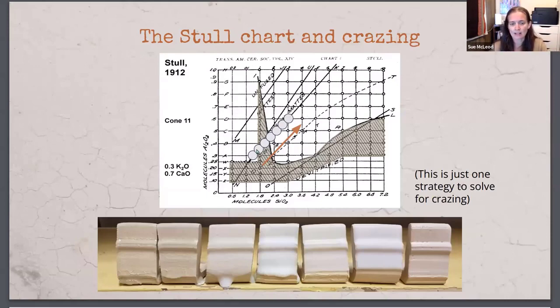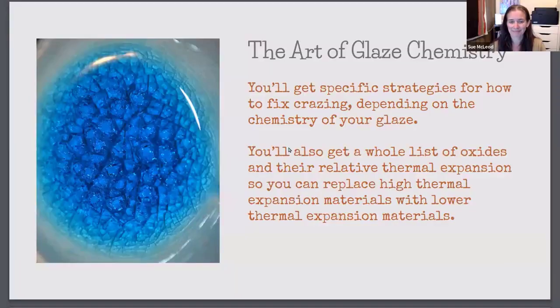And so all of these dots represent these test tiles, and you can see my test results show crazing on the first three. So these three are crazing, and then these four, the four top ones, are not. So in this case, my glazes are crazing in Stull's crazing region, and then they're not crazing as soon as I get out of his region. But I also have examples of where crazing can kind of happen over here. And it's based on the other materials that are in the glaze, not just the silica and alumina.